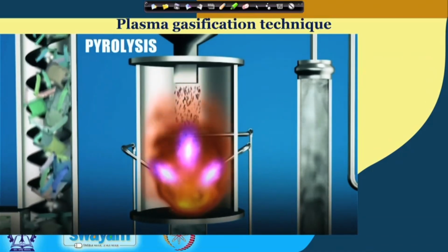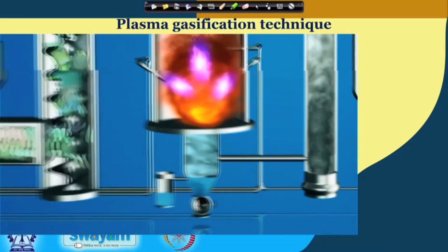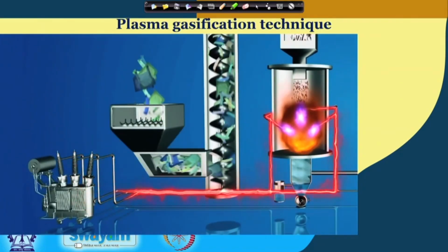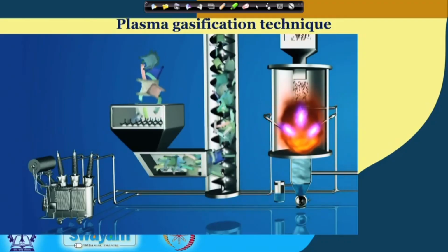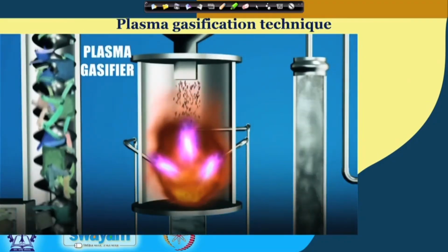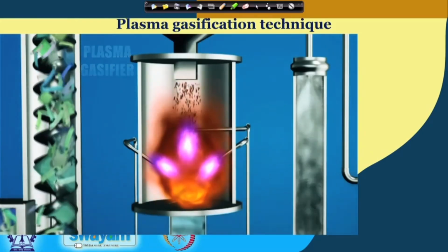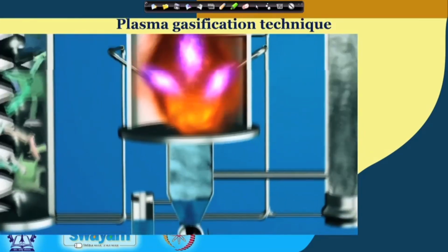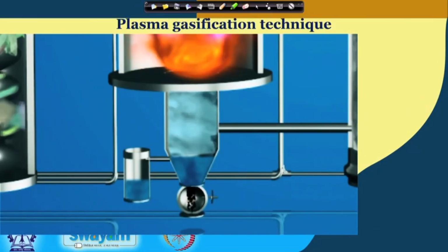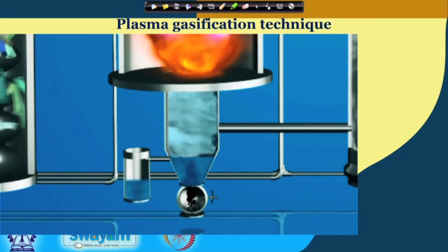The pyrolysis reactor is the heart of the system, consisting of a cylindrical chamber with a tapering bottom half. A transformer supplies the necessary voltage to the graphite and carbon electrodes fixed inside the gasifier. As a result, a very high temperature, over 3000 degrees Celsius, is generated at the sparking zone. A slag removal system at the bottom of the gasifier drains slag continuously into a water pot.